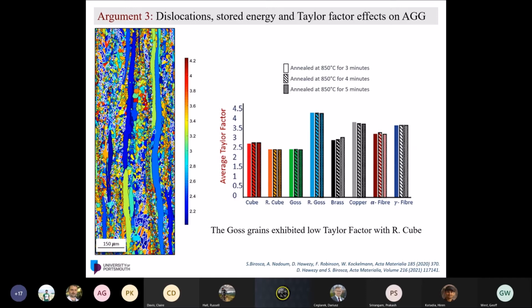So that theory of having high dislocation density, which shows high stored energy, and then a higher Taylor factor, makes sense during the recrystallization stage, but we couldn't find any evidence that it has any influence during grain growth. So now we try to develop our own theory about this.